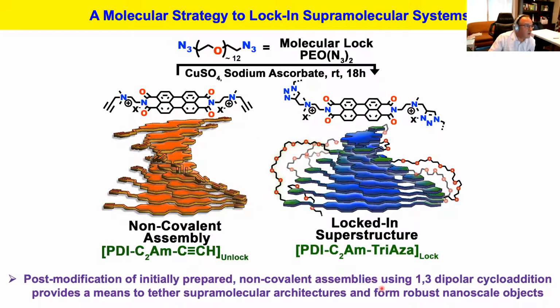So now what we can do here is, once we have preformed our assembly at a given concentration, I can start coming with what we are calling a molecular locker. We can call that a tether, and if people in the protein community are here, that's essentially what we are doing when we are stapling proteins. And so now you have this molecular locker with 12 to 13 repeating units, and you have this azide functionality. And essentially what is happening is that we are reacting this triple bond in order to form a triazole, and we are tethering the supramolecular polymer together. And so what I'm going to show you over the next couple of slides is that we are essentially accessing different material compositions by doing that.